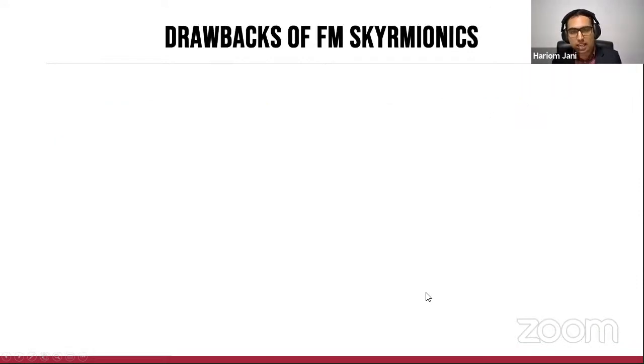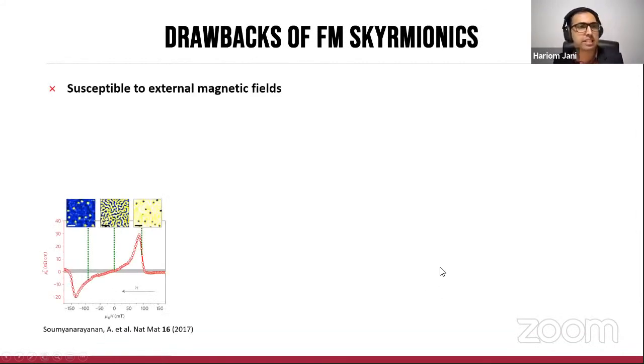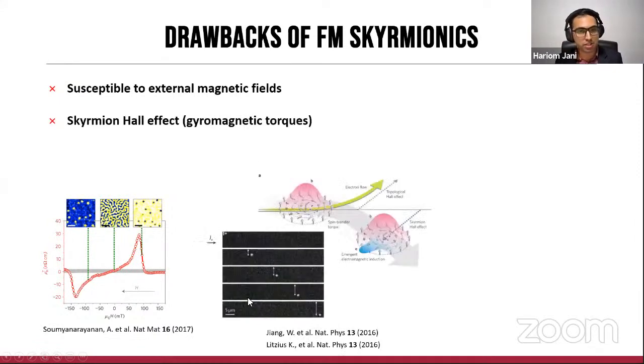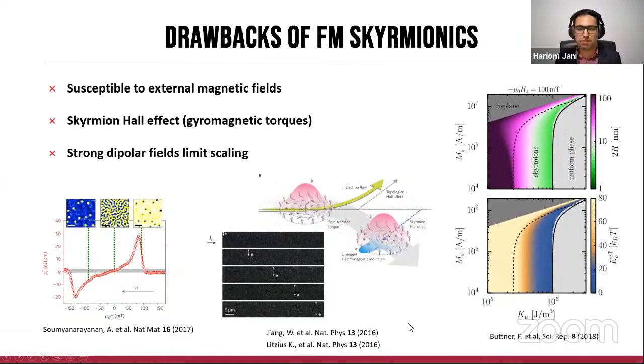Now, that said, there are some fundamental drawbacks of using purely ferromagnetic textures that I would like to quickly highlight, which is firstly that they are very strongly susceptible to external magnetic fields. Not always, but often they require the presence of fields for their stabilization. They exhibit the skyrmion Hall effect, which is a transverse deflection of the object when driven by currents because of gyromagnetic torques, and also the presence of long-range internal dipolar fields restricts how small the textures can be made, therefore prompting us to look at alternative ways to realize topological textures, and that has really brought a strong attention